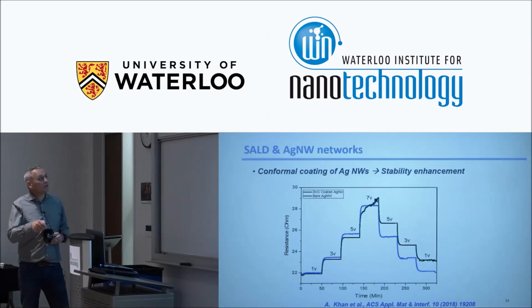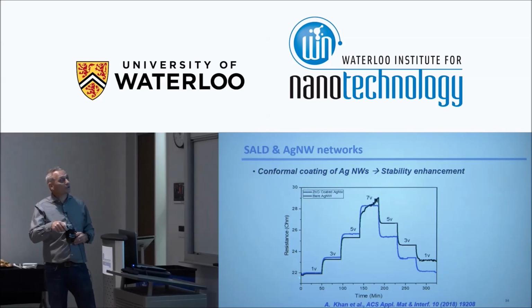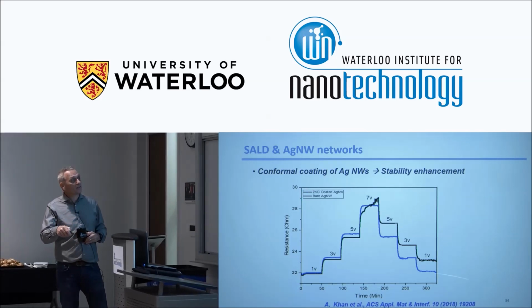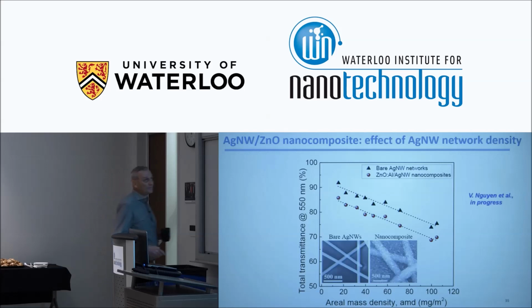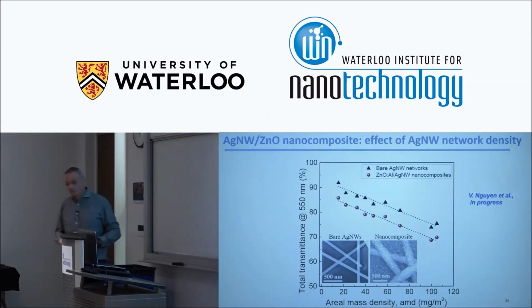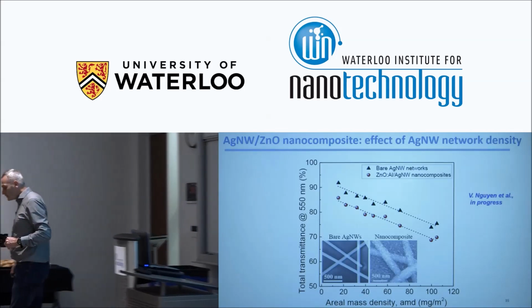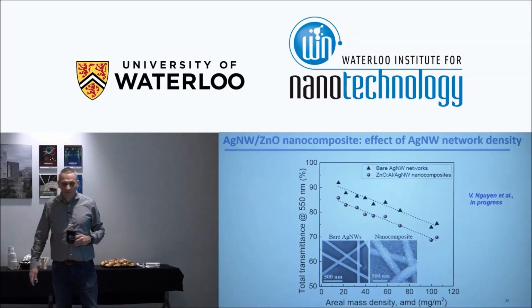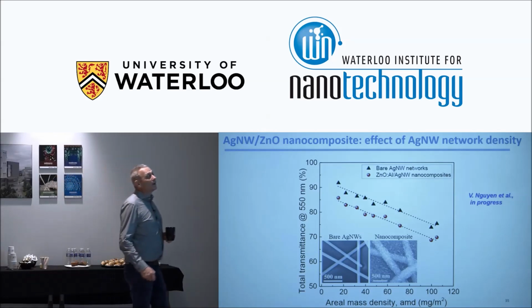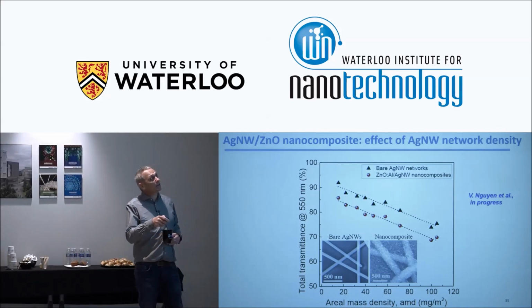And now if we do the same as before, measuring the electrical resistance versus the time, for bare nanowires, that's in black, we can clearly observe some non-stability, and in yellow with the zinc oxide coating, we can see that it's much more reversible. So we went on working on this, and I think there's an interesting field of research concerning silver nanowire networks. This is why we can make some nanocomposite with an oxide as well.